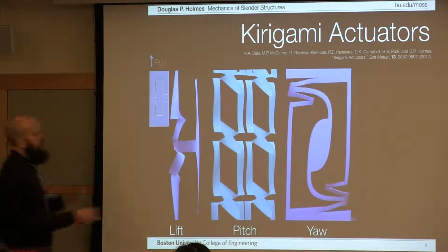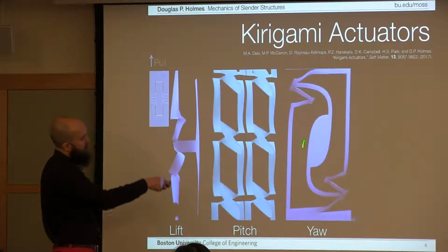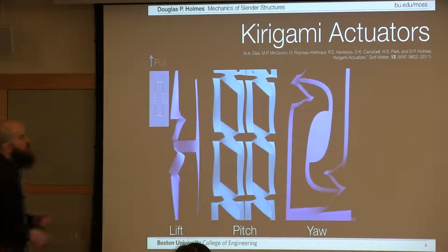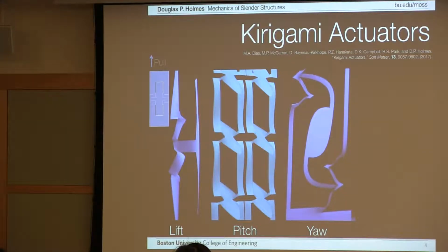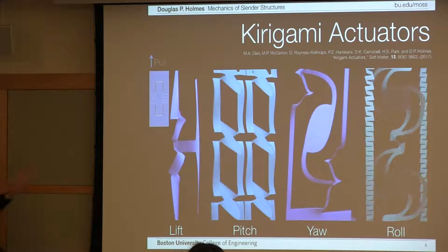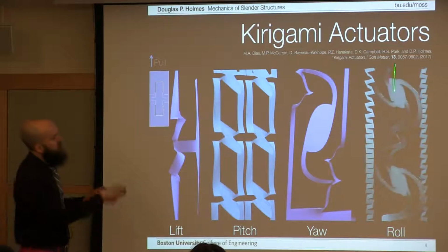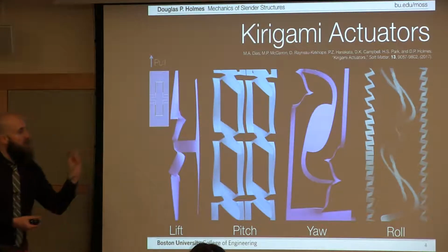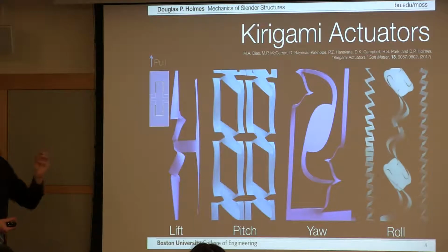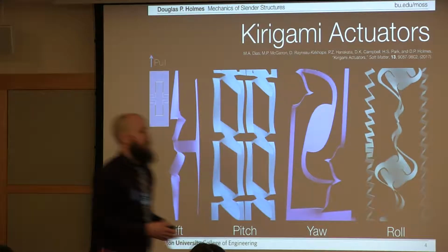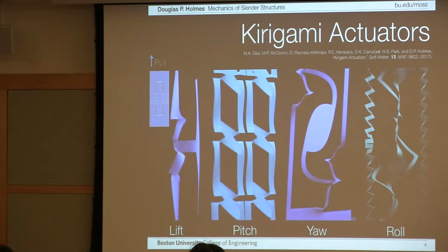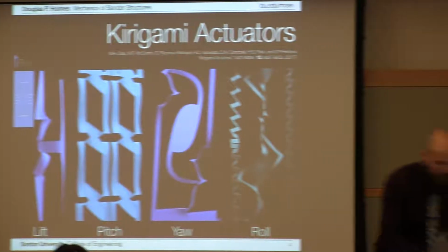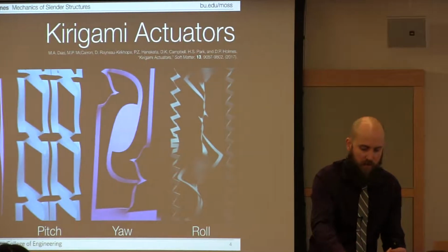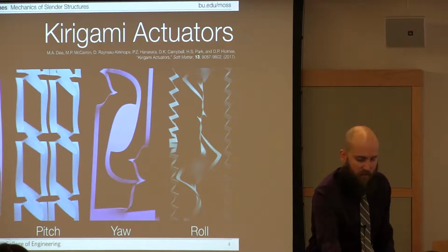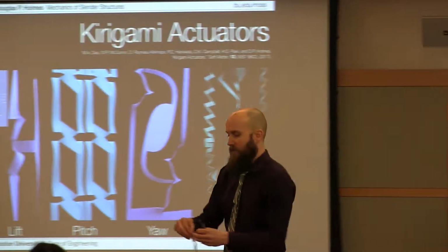Lift, pitch, yaw, this was the trickiest one. You get a tiny amount of rotation of this structure in the middle here as you pull on it. And even something as complex as roll, in which you were pulling on this thing vertically and we're taking a part of the sheet. And just by putting cuts in a particular pattern, you can cause this thing to spin around. So let me pass around a couple of these so you can play with them and see if you can figure out how you should arrange these cuts to get them to do certain things.